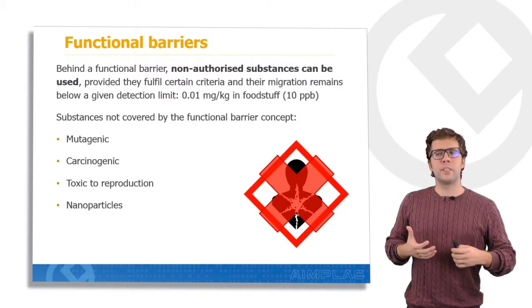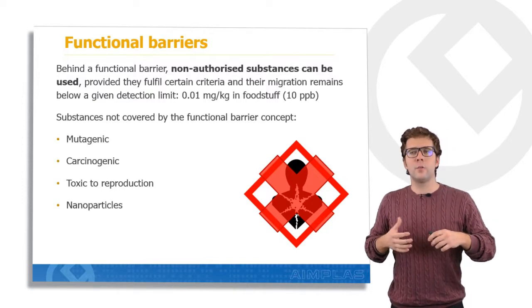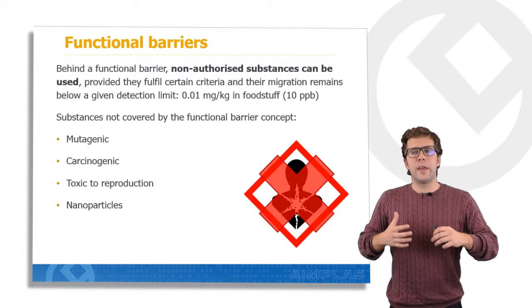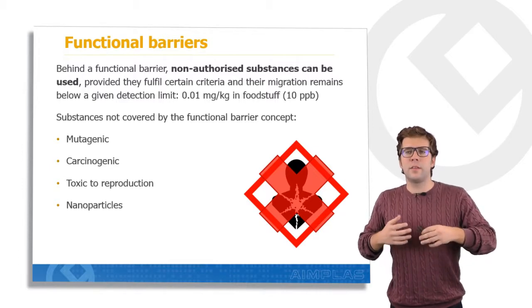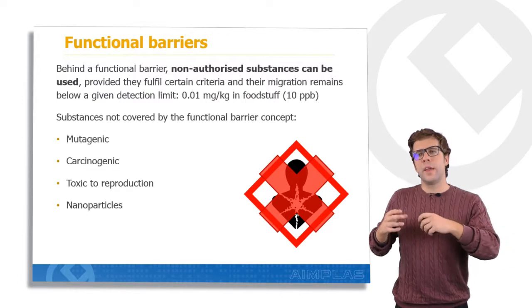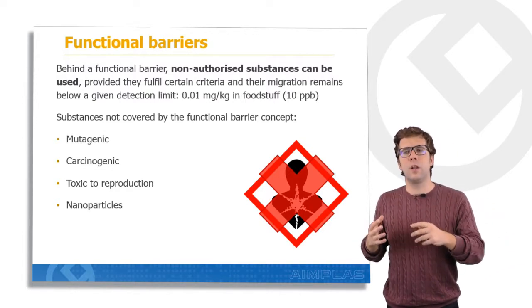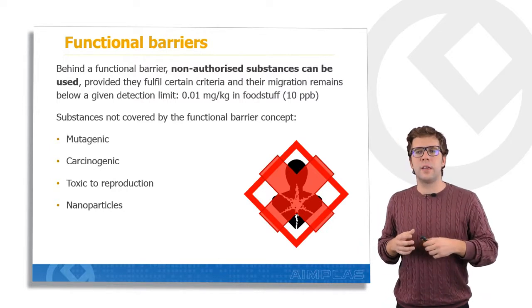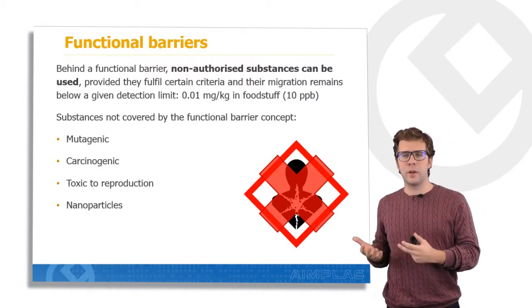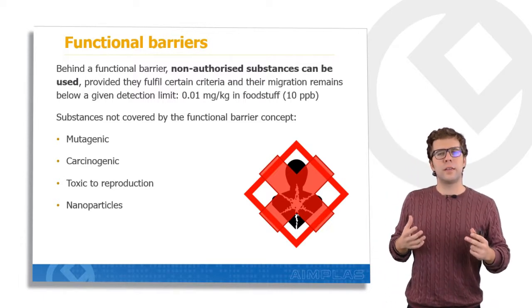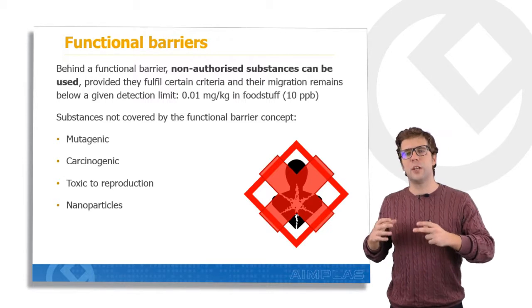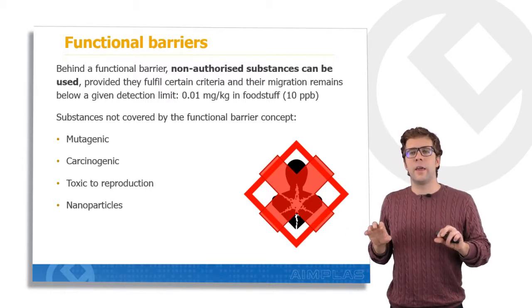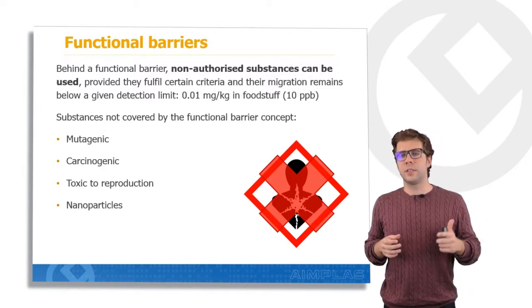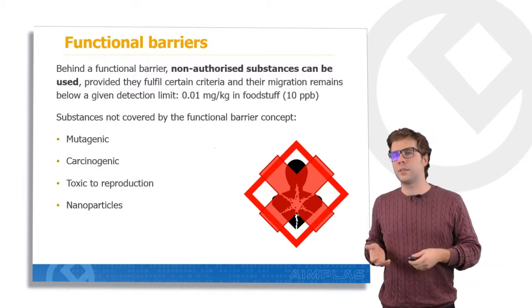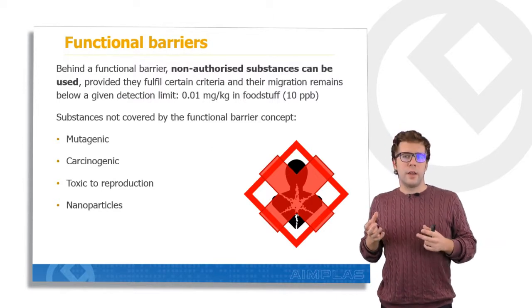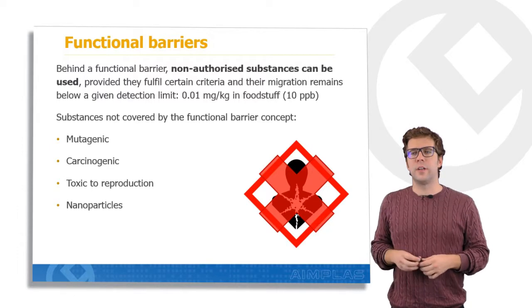Behind a functional barrier, it is possible to use non-authorized substances, provided that they fulfill certain criteria and provided that the functional barrier is able to prevent the migration or to keep that migration below a given detection limit. In this case, the detection limit is 10 parts per billion. But it should also be noted that not all substances are covered by the functional barrier concept. There are some substances, like mutagenic substances, carcinogenic substances, substances toxic to reproduction, or nanoparticles, that cannot be used under this concept of functional barrier.